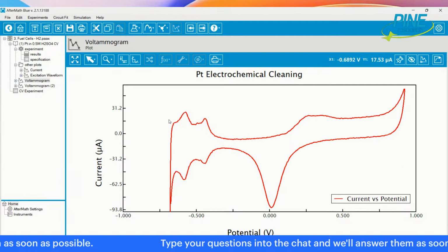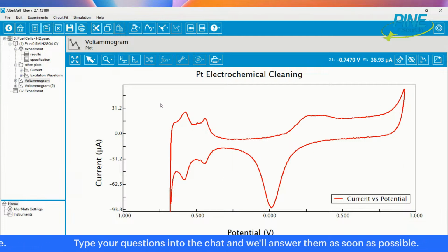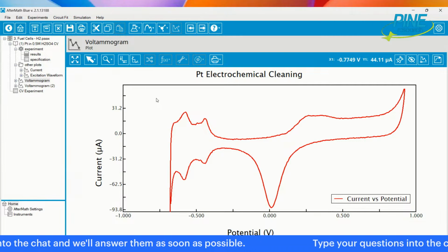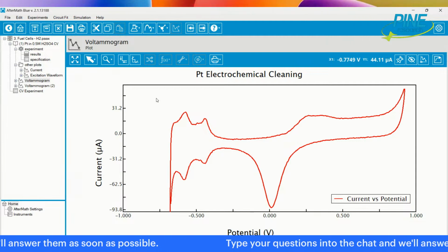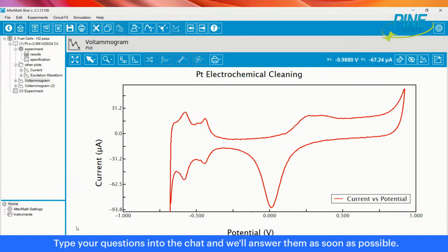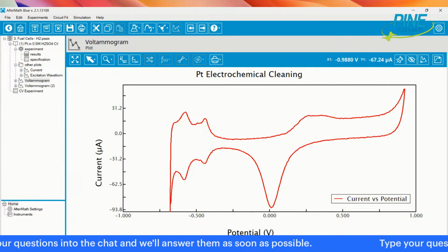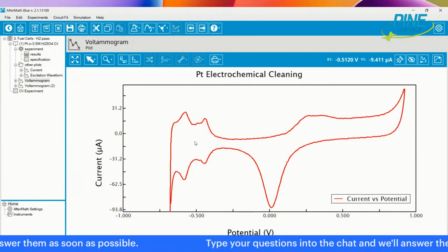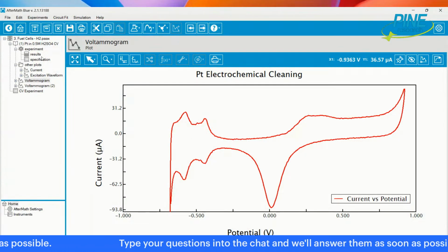And that has a well-established specific charge value of 210 microcoulombs per centimeter squared. That's the number. I have the papers, I can pull them up in a bit, but I want to show you the calculation. That's mainly what I think this question was. They wanted to see how this is done physically.